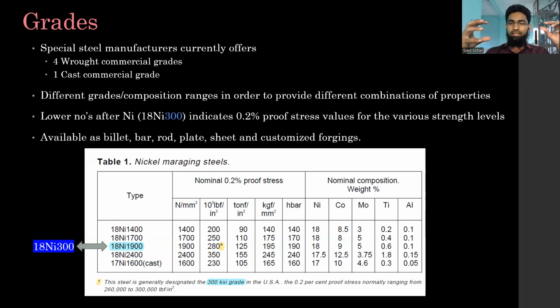The strength achieved will not be as per the guidelines laid out. What happens is, if the composition is set to be so and so, then the strength achieved is so much. So that will not happen. That's what we mean by composition sensitive. And this steel is extremely composition sensitive. Any application engineer will have a desired set of mechanical properties for an application. But if there is non-optimal chemical composition, you will not be able to achieve it for composition sensitive materials. And this is one of them. So that's one limitation you can call it.